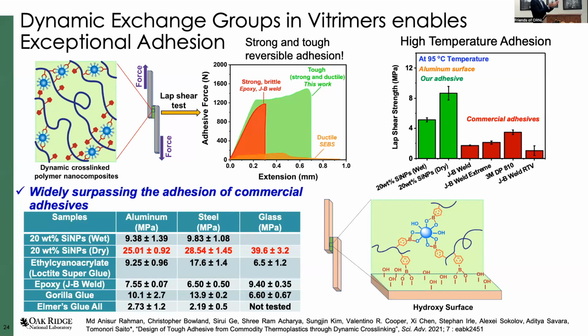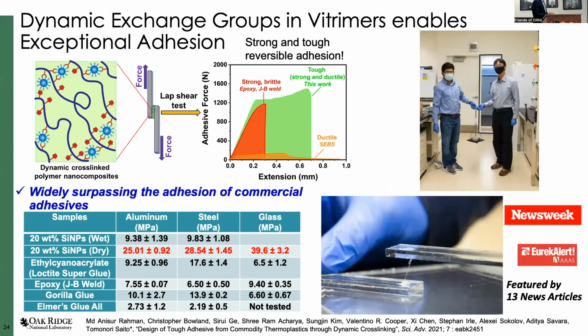I had one slide talking about the extended temperature range. This is when you go to 95 C. This is still pretty high. This is our data compared with commercial products, which tend to become soft. So that's quite useful, even at high temperature, for these materials. Okay, this highlights some of the articles about it. Again, it's very strong adhesion, but you can recycle and reuse it, potentially starting from plastic waste.